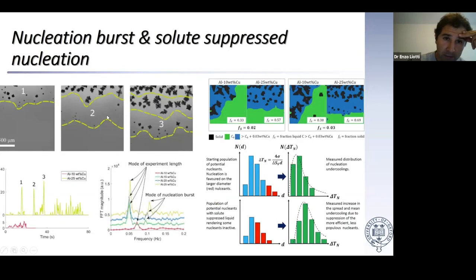Again, applying this methodology to all the 128 datasets, we found that these waves or bursts are correlated to the solute content, both in intensity and in frequency. Therefore, increasing the solute has the effect of increasing the intensity and the frequency of these bursts, and therefore increasing the number of grains forming. So essentially decreasing the grain size. And we also developed our own empirical model to describe the effect of cooling rate and the effect of solute in terms of nucleation.